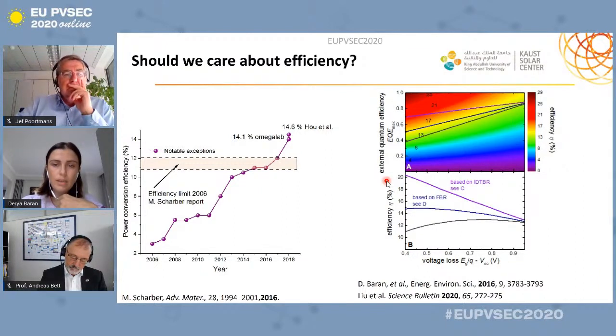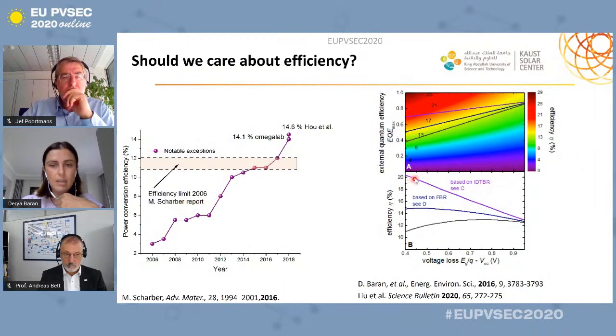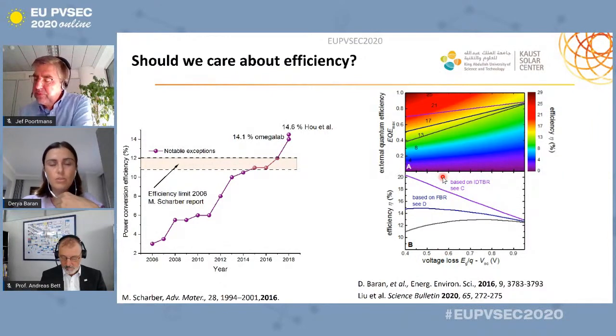And we made a quick estimation of actually where OPV can go with this new type of acceptors now. And we have seen that it is sort of possible to achieve around 20% power conversion efficiencies if we could actually mitigate or eliminate this 0.6 eV voltage losses in these particular solar cells, which was sort of hypothetical at that point because it was known that you need around 0.3 eV for the efficient exciton generation, etc.